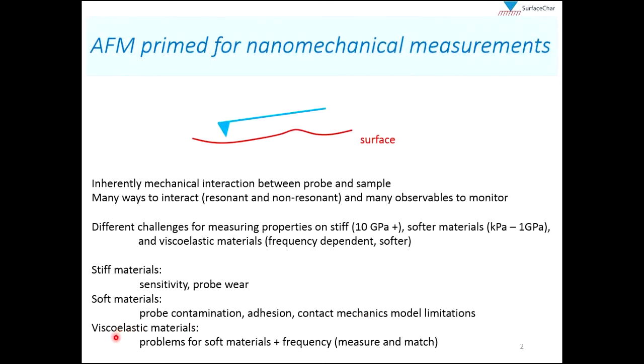Finally, for viscoelastic materials, AFM faces all the problems for soft materials, because most viscoelastic materials are soft. But now we also add a frequency problem, both for measuring the frequency, in other words, knowing what frequency the sample is experiencing during the AFM measurement, and then also matching the frequency. So AFM measurements happen at a certain frequency, and you might want to match the mechanical properties to other techniques that operate in a totally different frequency regime.